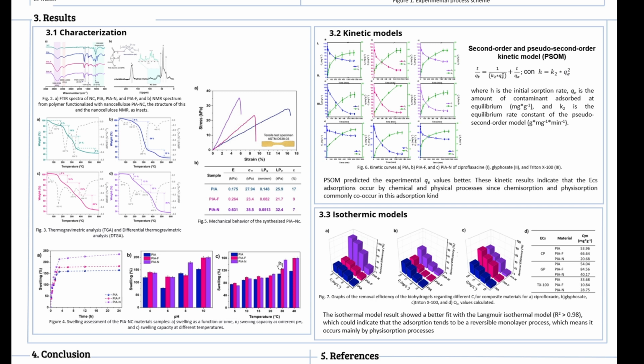For the polyitaconic acid nanocellulose biohydrogel, the first step corresponds to water evaporation absorbed by the hydrophilic polymers. The second step agrees with carbon-carbon bond cleavage depolymerization, leading to a broad degradation intensity compared to the pure nanocellulose. Due to such broader degradation behavior, the third step of degradation corresponds to decomposition and combustion. The figure also showed that the composite materials increased thermal stability after adding the nanocellulose.